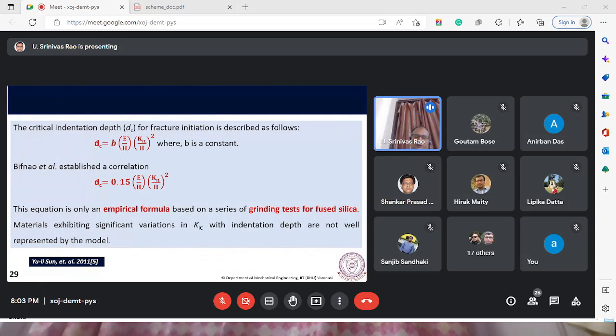So through all these experimentations for different materials, this DC, the critical indentation depth, is found. Okay. So it is being done continuously. From those, as I already mentioned, Bifano formulated this. In that, this constant is material specific, so that has to be obtained through experimentation only. The experimentations may be a grinding test, an indentation test, or a scratch test. These are different tests to get the critical depth of cut.